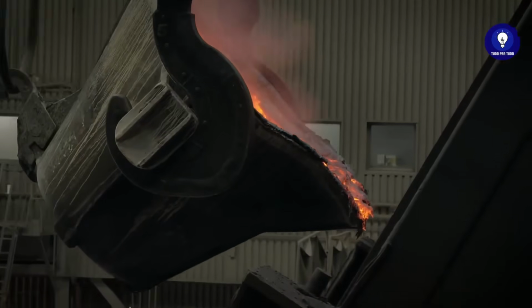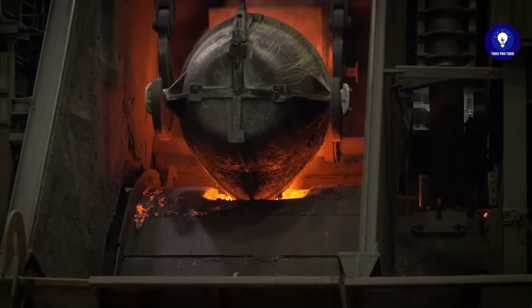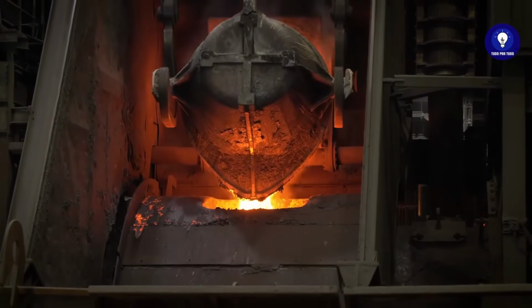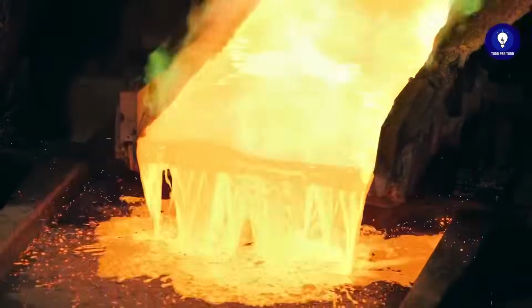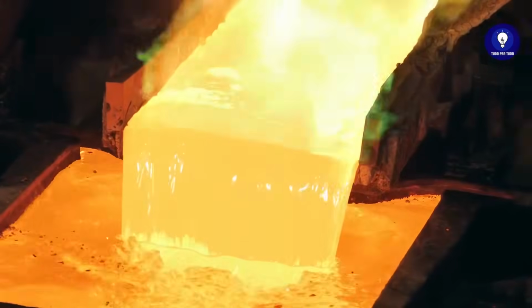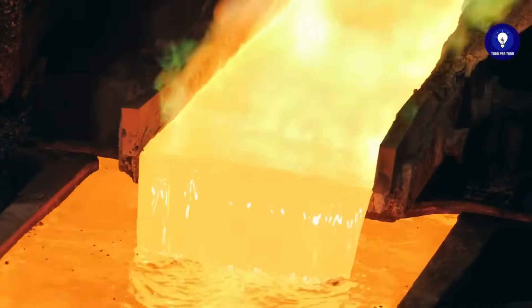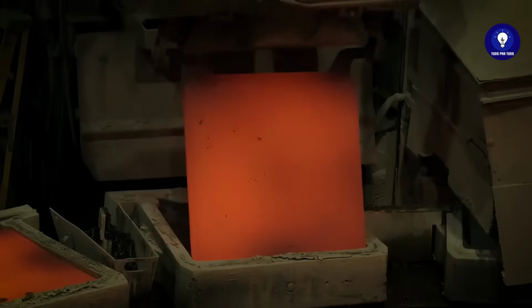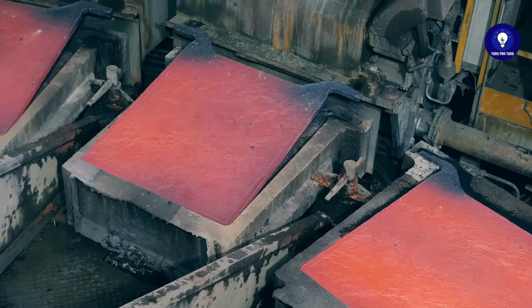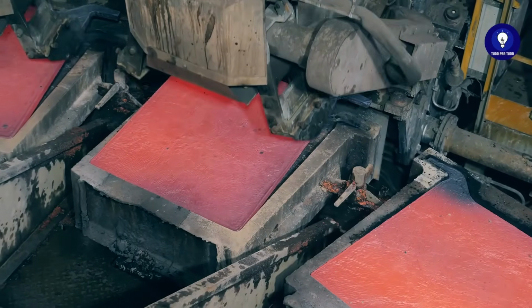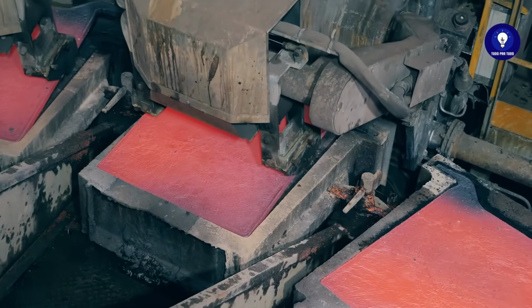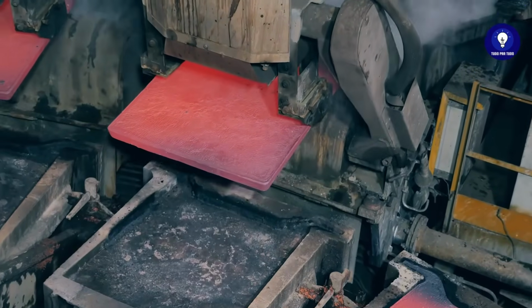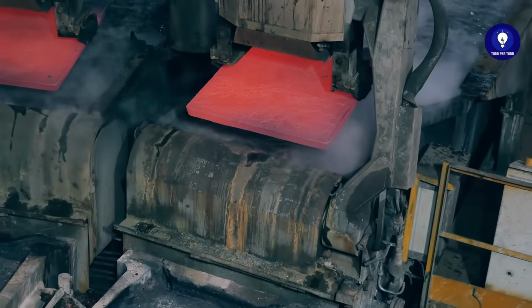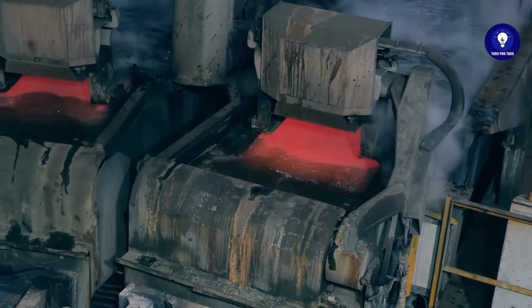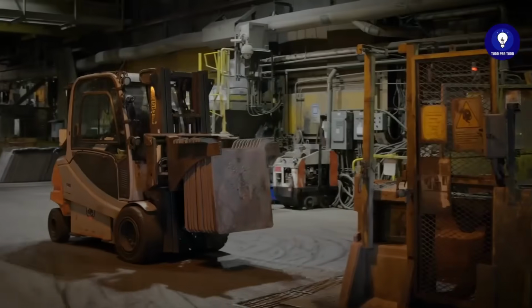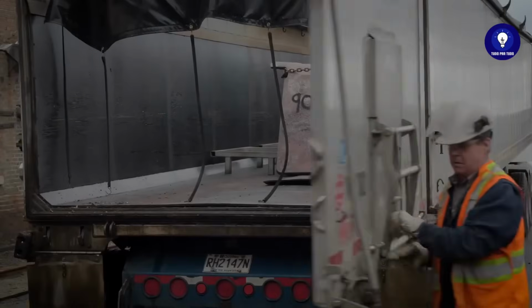Meanwhile, a crane transports liquid copper to another furnace, where the final purification is carried out. The purity increases to 99%, and the molten copper is poured into molds, forming large rectangular plates called anodes. These plates are cooled with water jets and solidify. A hydraulic cylinder ejects them from the mold, and an automated system transports them to a rinsing station, where the residues of the release agent are removed. Afterwards, they are sent to a refinery hundreds of kilometers away.